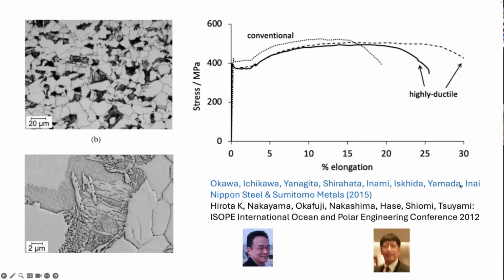And that has happened. We can now greatly increase the ductility of ship steel. You can see the strength is about 400 megapascals. The reason is that the conventional ship steel has a structure like this, which is ferrite and pearlite. Pearlite is simply a mixture of hard cementite and ferrite. Because there is a big difference in strength between the ferrite and these hard regions, they don't deform homogeneously, and therefore you have limited ductility in a tensile test.